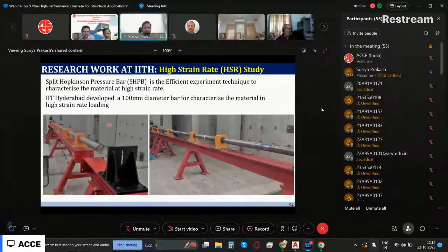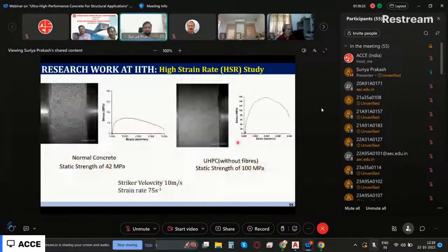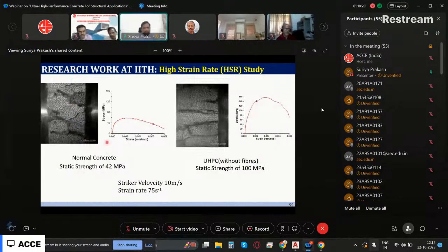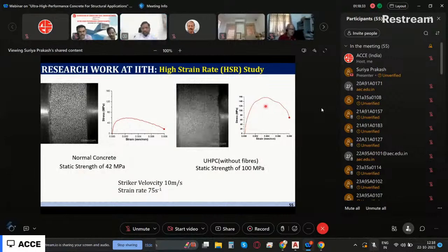This is one facility that we have created in IIT Hyderabad. This is called the split Hopkinson pressure bar setup, and this can be used to test material. And this is a figure that we are showing. Normal concrete fails at a very low strength. But you see, if I test it at the same velocity, UHPC is able to give a strength much higher than that of the normal concrete.